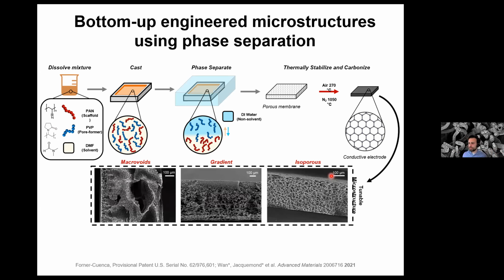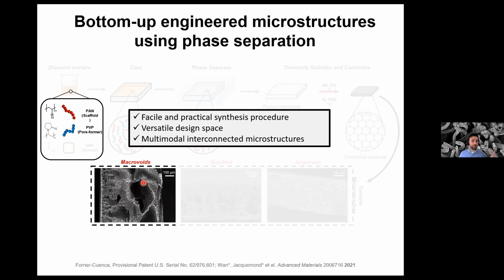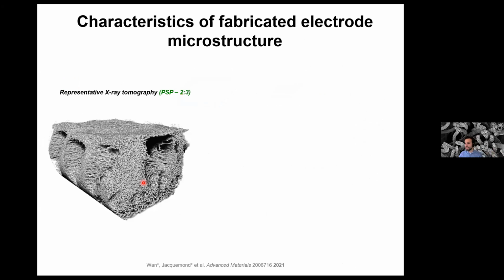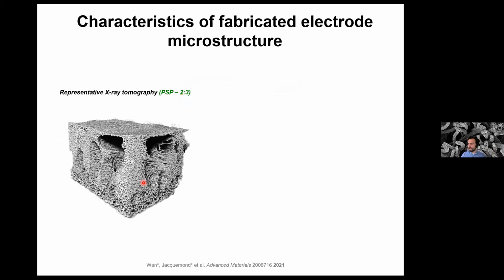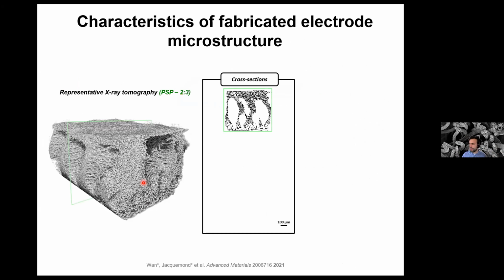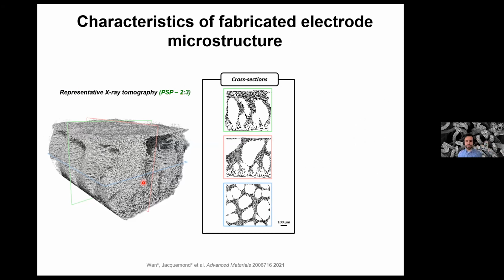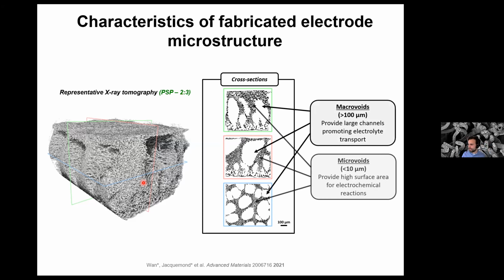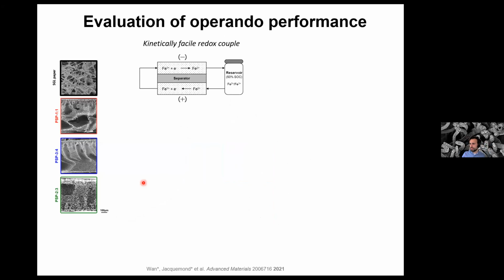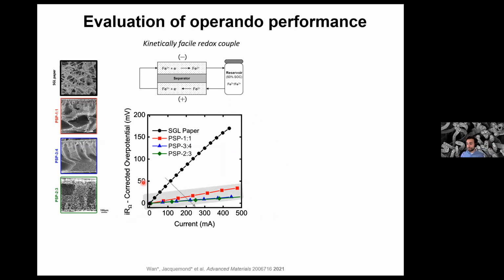And by changing a few easy parameters, we were able to produce isoporous structures, structures that have a porosity gradient, and structures that have these big pores, these microvoids. And we think these are desirable properties for electrochemical systems based on the theory that has been developed in the field. So we just tested this material that resembles a sort of honeycomb, because it has these big pores through plane, and then it has these small pores in between. We tested these materials in flow batteries recently, and we were able to see, this is particularly for an iron chemistry, that the performance goes up by a lot. So the overpotentials are reduced, and there is a lot of work on optimizing the surface chemistry that needs to be done, but the starting point is already very interesting.